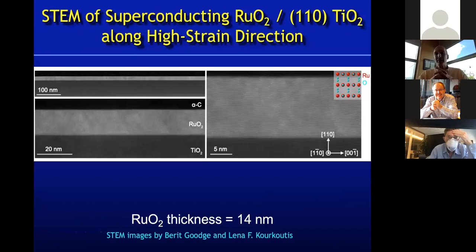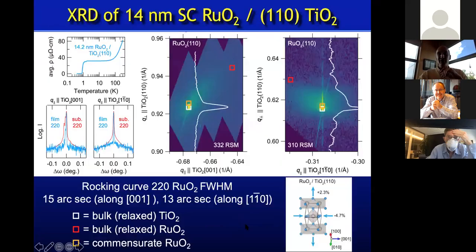Our electron microscopy collaborators have had a look at this. These strains are huge. Okay. Here's the ruthenium oxide film looked over a wide range, and if they zoom in, there are regions that look well ordered. There are also some regions that don't look as well ordered. Okay, but I'm showing you representative regions of the film, and notice it's very thin. When the film gets thicker, it definitely starts to relax. We've gone to the synchrotron to have a look at the relaxation.